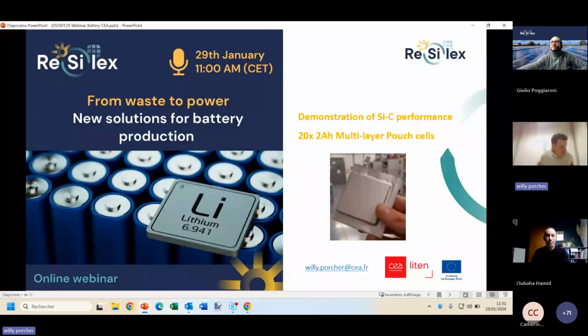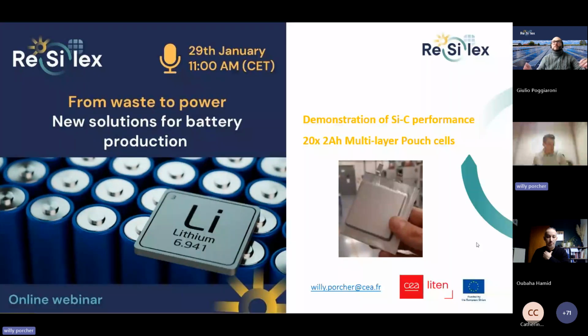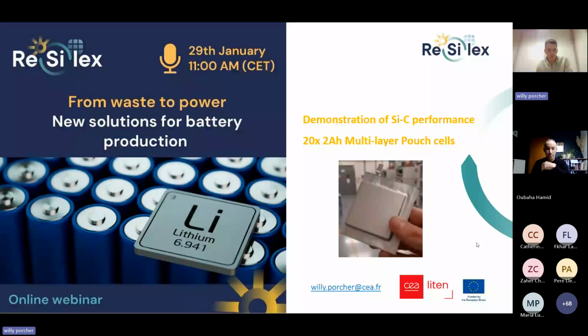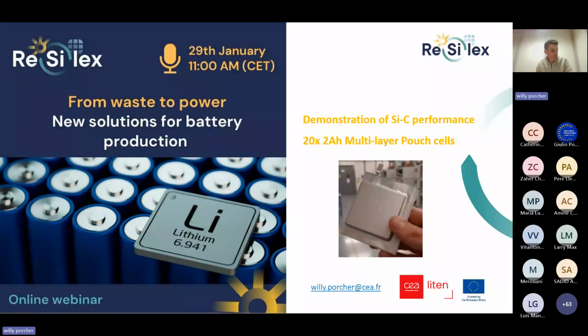So, after Hamid's presentation on silicon carbon composite development, I will show you our contribution in the Resilex project with demonstration of performance in multi-layer pouch cells of 2 ampere hour. So we assembled more than 20 cells. A 2 ampere hour cell is typically what you have in your smartphone. Here it's cells of 5 by 5 centimeters with 5 millimeter thickness. So it's small cells, but it's a factor 1000 compared to the coin cells presented previously by Hamid.